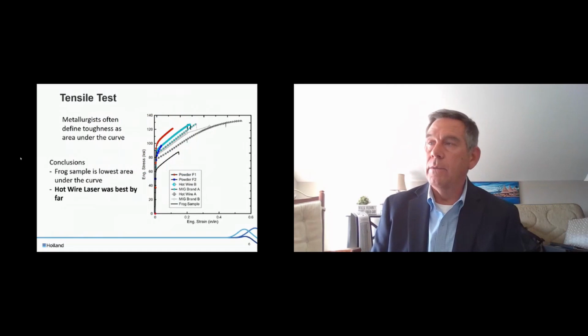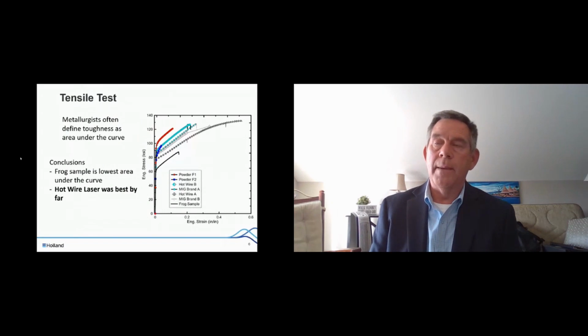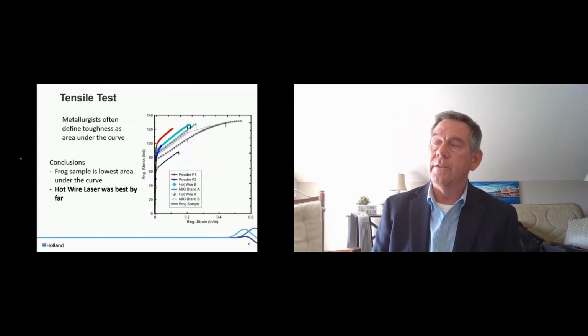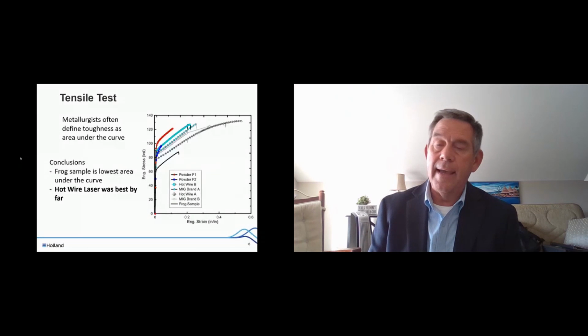The next test we utilized was a tensile test. Metallurgists often refer to metal toughness as the area under the stress strain curve from a tensile test. It's one of the reasons why manganese is used for this application, because of its toughness. So if we look at, again, comparing this to base frog material and other materials and processes, just to summarize quickly, the lower part of the lower graph, coming off of the 60 KSI, is the base frog material.